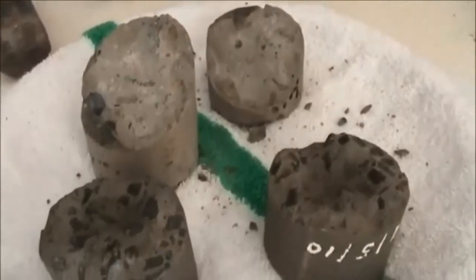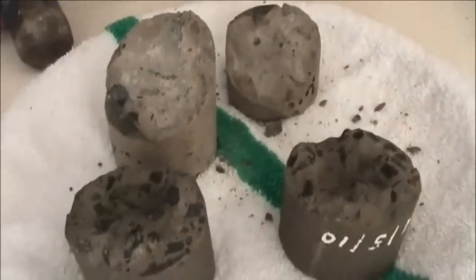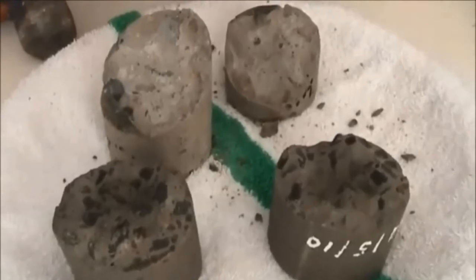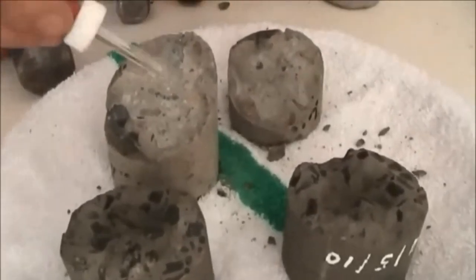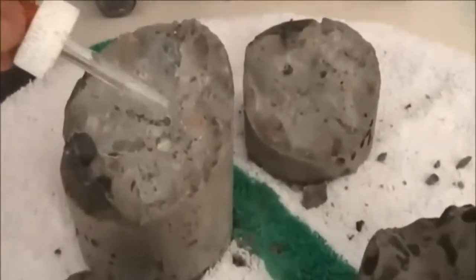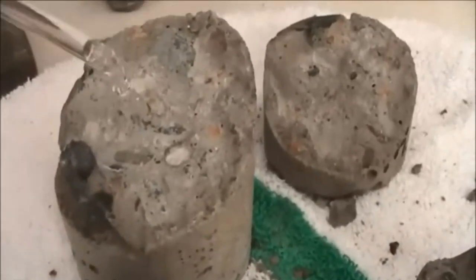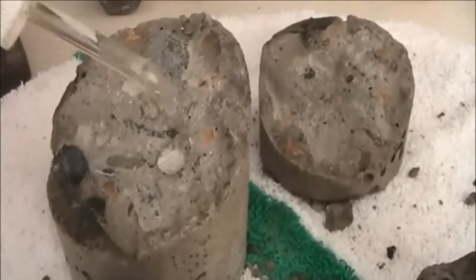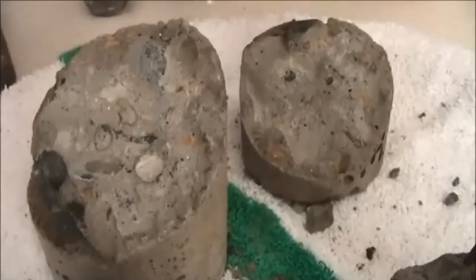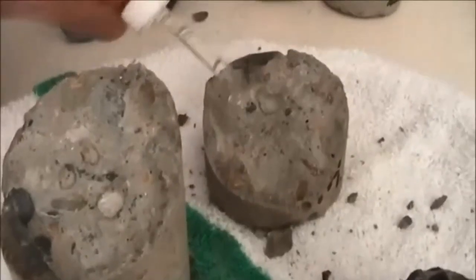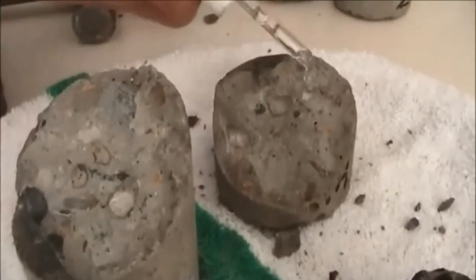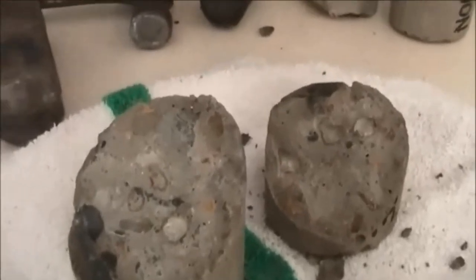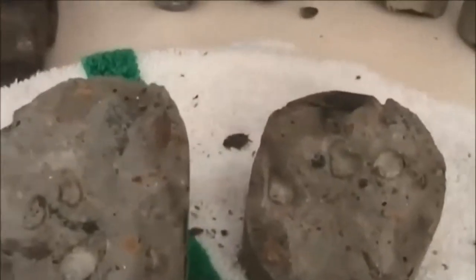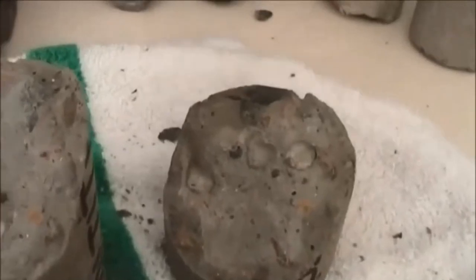Another very simple test, if you actually put water onto that. See how it beads, sits up, is completely water repellent, even after being underwater for 7 days. We've actually extended this test, particularly for up to a year in our laboratories in Singapore. I didn't manage to get hold of any photographs, but they're still doing the same after being underwater for over a year.